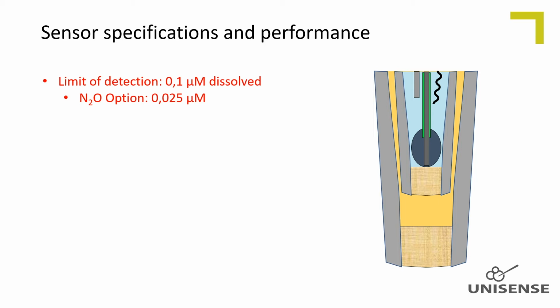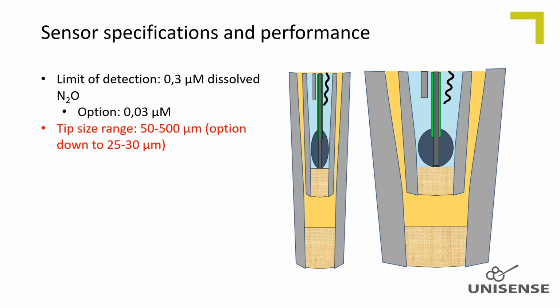The largest version can be made with the larger chip membranes, achieving a detection limit down to 25 nanomolar in a low-range version. The standard chip size ranges from 50 to 500 micrometers. We produce them in standard models with 50, 100 and 500 micrometer chips. We can, however, make them with chips down to 25 to 30 micrometer. Naturally, the smaller the chip is, the more fragile it will be.